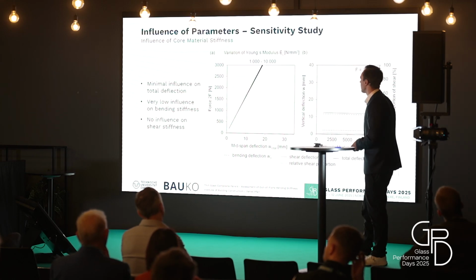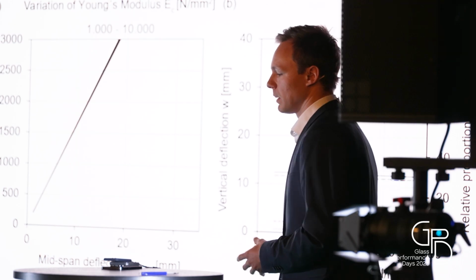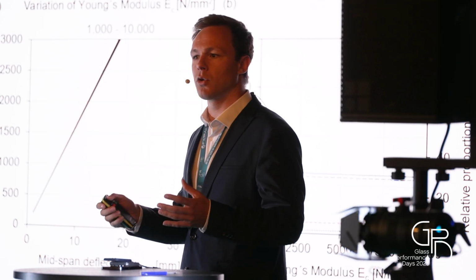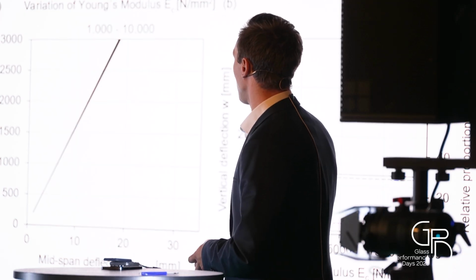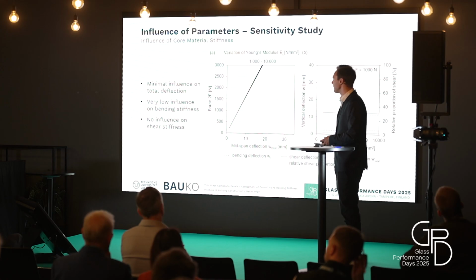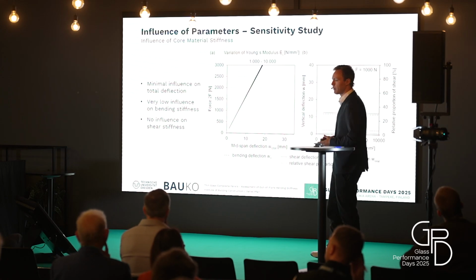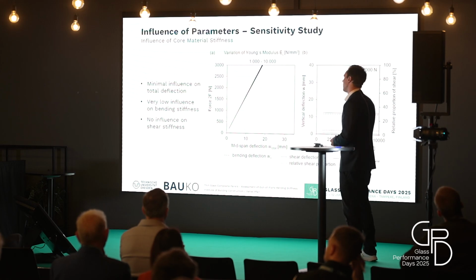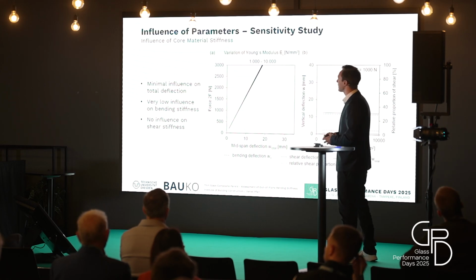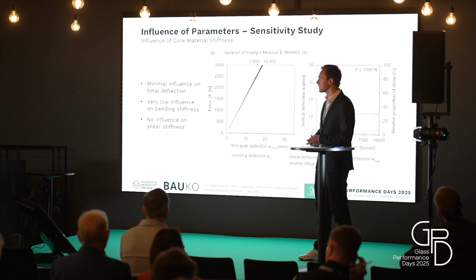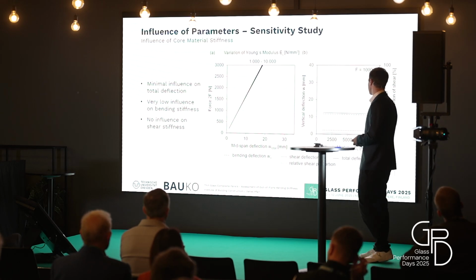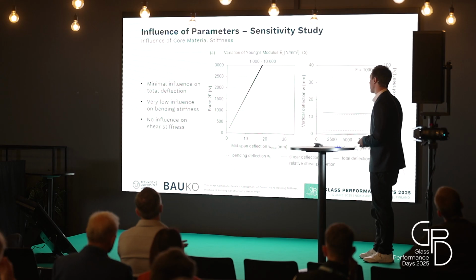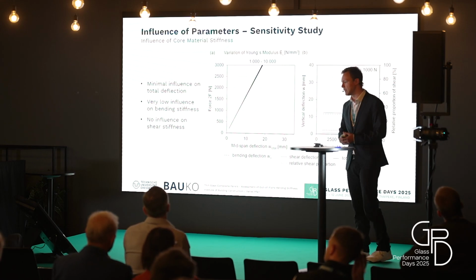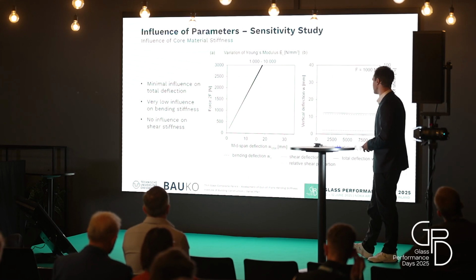The second one is the variation of the Young's modulus of the core. So we expected that the core depends very much on the material we are using and printing. But in that case, we have varied the Young's modulus between 1,000 and 10,000 Newton per square millimeter. And we can see there's almost no variation in the bending stiffness or in the deflection of the tests. So we can say that we have only a minimal influence on the total deflection. And looking at the right-hand side of the diagram, we can also say that we have a very low influence on the bending stiffness and no influence on the shear stiffness.